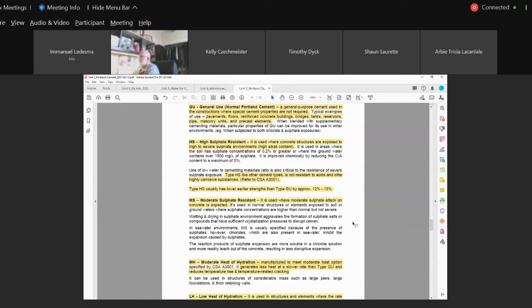Just to check it and make sure everything's okay. But how's that going to dictate? How do we know that? To predict the final strength. Exactly. We know that if we're going to get 70 to 73 to 75%, that's the relationship between 7-day and 28 days, we can use it to predict. If we got a 7-day strength at only 50% of the anticipated design, say 35 MPa, we might say, we got some problems here. What happened? Doesn't mean the 28 days isn't going to make it. Maybe there's something wrong with the 7 days, but it's used to predict, are we going to have any issues at 28 days? Are we going to achieve our 28-day strength? Because we know the correlation between 7 and 28.